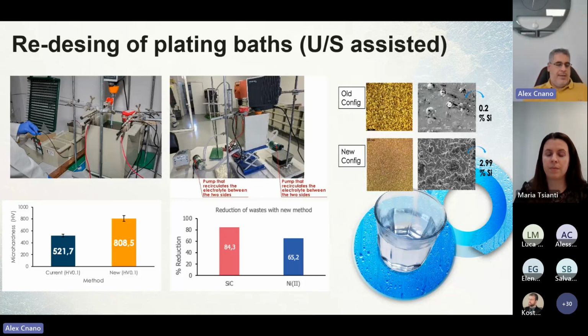And of course, this is translated, as you can see, to a better hardness, a vast increase of the hardness from 500 to 800. Additionally, we can have reduction of the wastes in the rinse tanks at a level of 85% for silicon and 65% for nickel, what we call the drag out phenomenon.